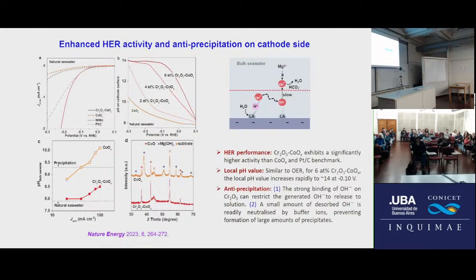So what is the reason? We measure the pH value in the bulk solution, not the surface. You can see, if we use cobalt oxide only and increase the current density, this concentration increases significantly. It goes above this dash line. This dash line is the precipitation line. So for this reason, cobalt oxide produces a lot of precipitation. However, in our case, even though the concentration in the bulk solution increases, it is much lower than the dash line. So in our case, we never found any solid product produced on the surface.